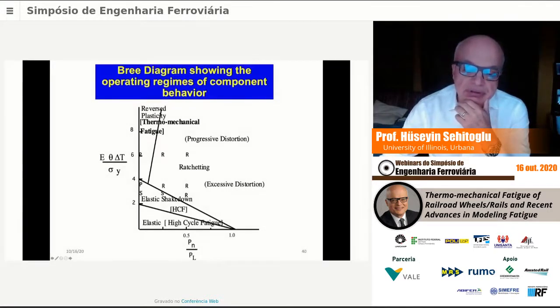In the case of a little bit higher thermal loads, as you go up the scale here, you get an elastic shakedown. In the first reversal, you get plasticity, but after that, you get elastic behavior. It's called elastic shakedown. If you have high loads and high temperature ranges, you get ratcheting in these structures. The PL here is the limit load. PN is the applied load. Sigma Y is the yield stress of the material. You get ratcheting here.